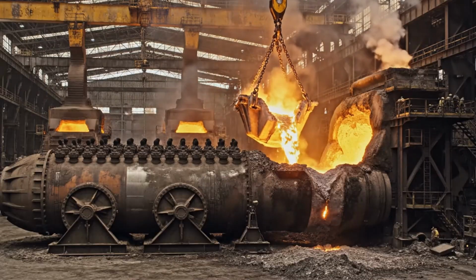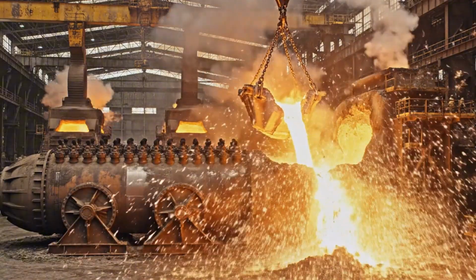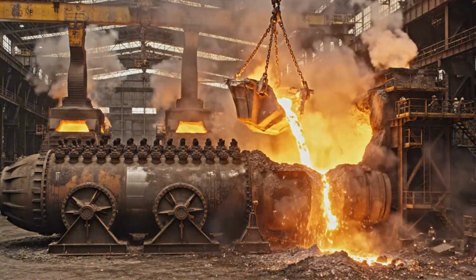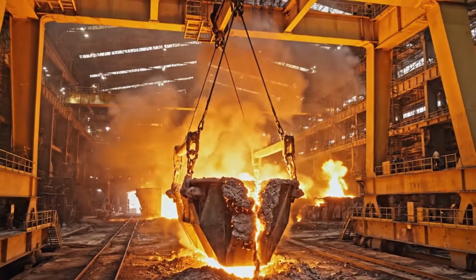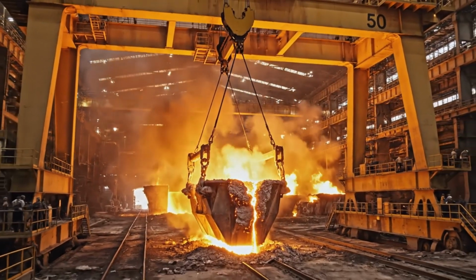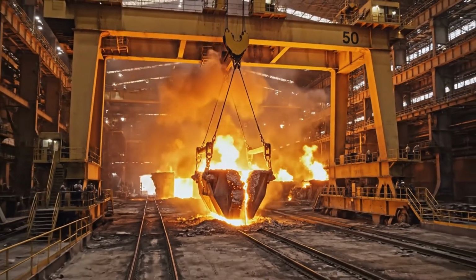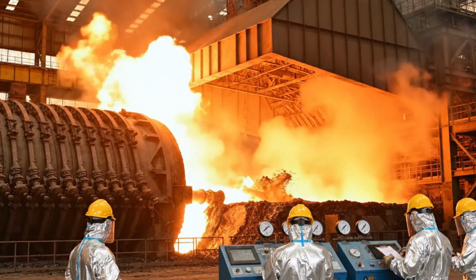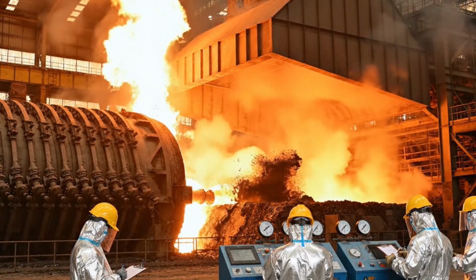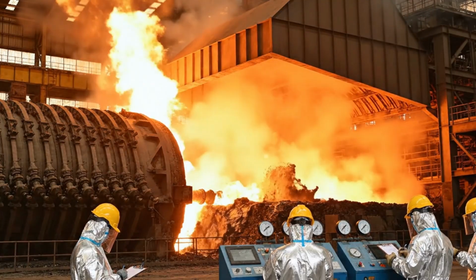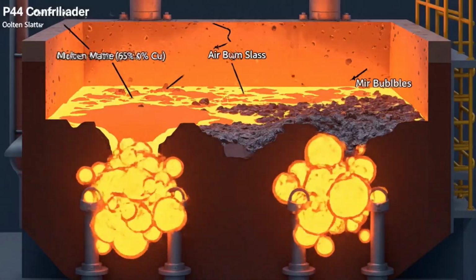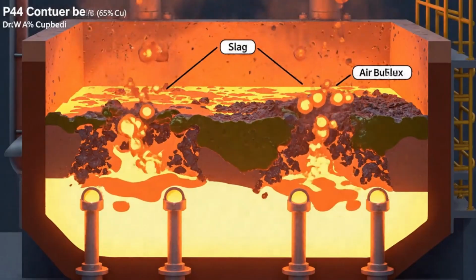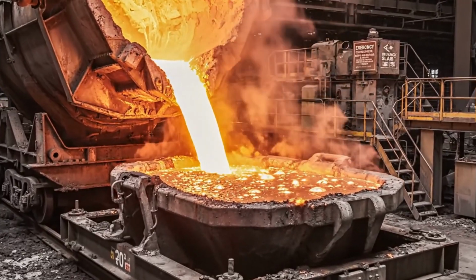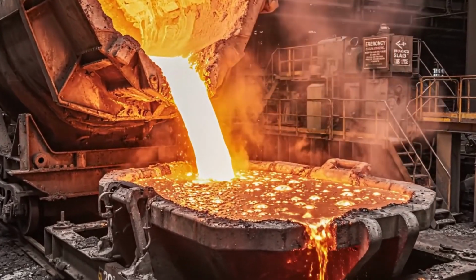Molten matte is charged into Peirce-Smith converters for the next purification stage. Overhead cranes carefully transport ladles of molten matte to the converter furnaces. Air injection oxidizes impurities, causing dramatic flames as copper is purified. Inside the converter, oxygen reacts with impurities, producing 98.5% pure blister copper. Blister copper pours from the converter, tiny gas bubbles creating its characteristic blistered surface.